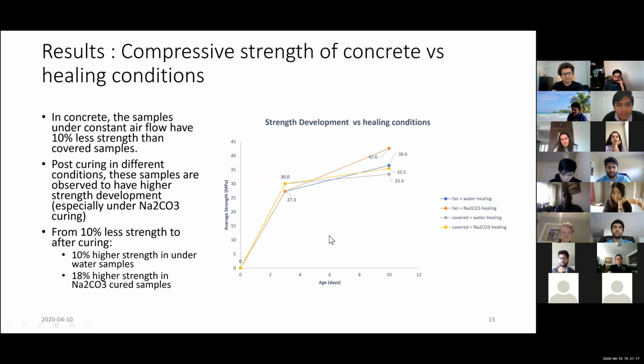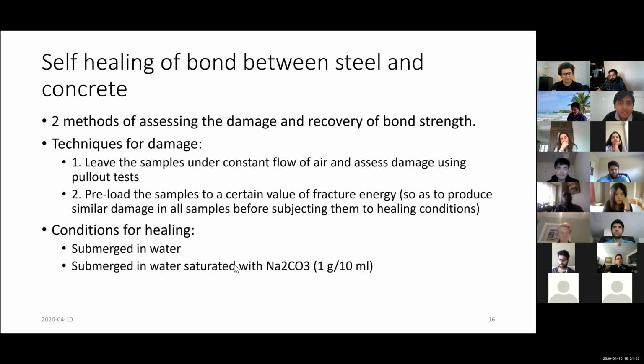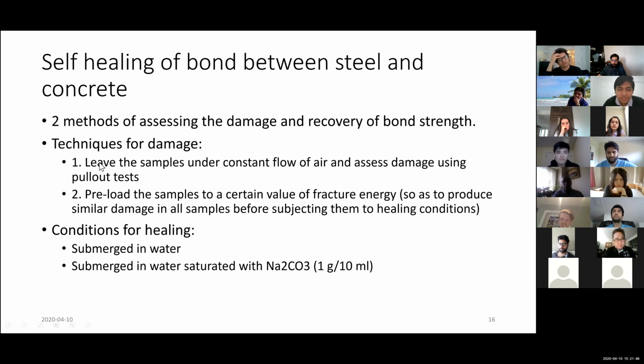So these are just some numbers that I calculated for the difference in the healing conditions. And so that was a shrinkage loss on concrete cylinders. In this test, I tested the bond between steel fiber and concrete. So there are basically two methods of assessing the damage. There are two techniques of introducing damage into the system.